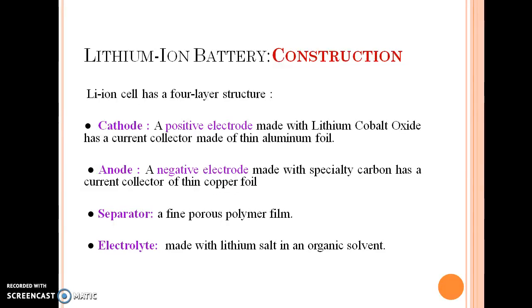It has a cathode, which is a positive electrode made up of lithium cobalt oxide, and a current collector made up of thin aluminium foil. The anode, which is a negative electrode, is made with specialty carbon and has a current collector of thin copper foil. There is a separator which is a fine porous polymer film, and the electrolyte is made up of lithium salt in an organic solvent.